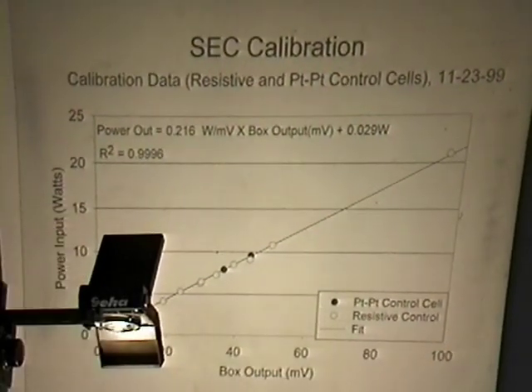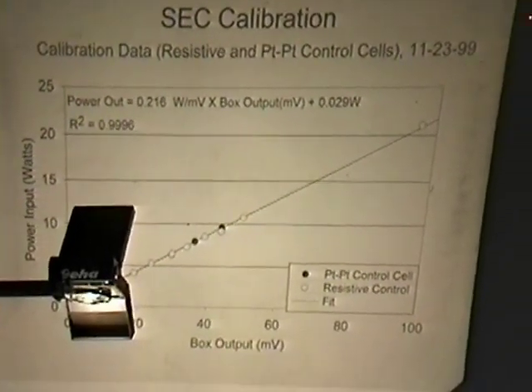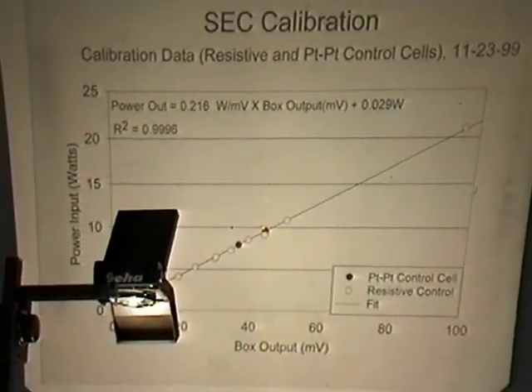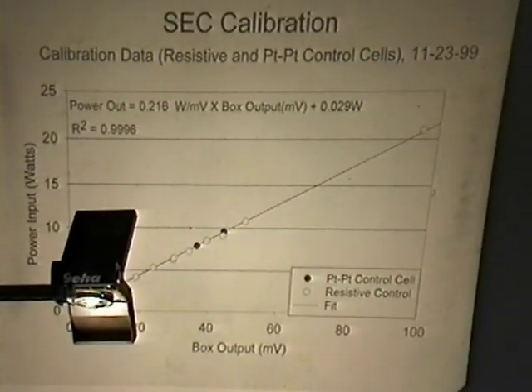Now, the nice thing about the Seebeck envelope calorimeter is it's fairly linear. Shown here represents 19 control data points. The dark areas, there's actually 3 of them, one's buried under here. The dark areas are platinum control cells, where we had a platinum cathode and a platinum anode. And we have 16 resistive control cells, resistors that were immersed in water. The line represents the fit. The fit is pretty good, and it's very close to 1.